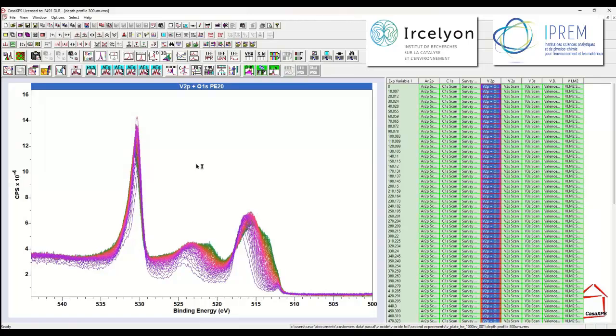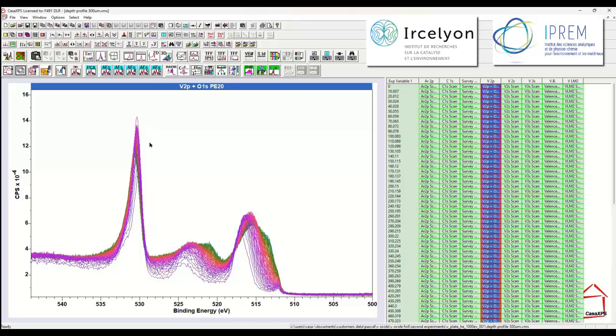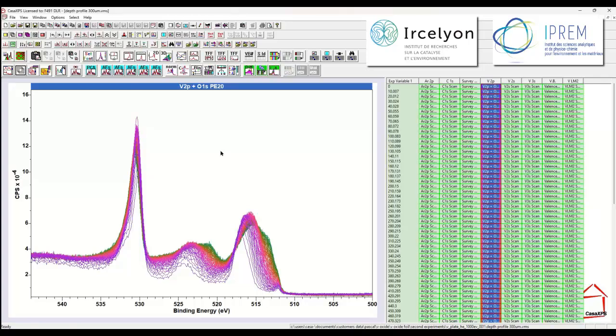The experiment that I looked at previously had data that were measured multiple times, but all the spectra were essentially the same, but for noise. And that's ideal if we want to test using PCA whether they are in fact identical, because the result of PCA applied to such data would be one abstract factor that would contain signal and very little noise, and then all the subsequent abstract factors would look like noise. This, however, is a dataset in which the spectra are evolving, and we will not find one abstract factor and the rest noise.